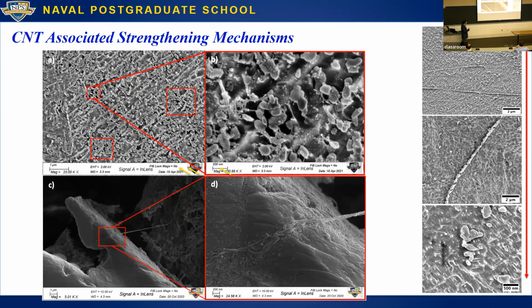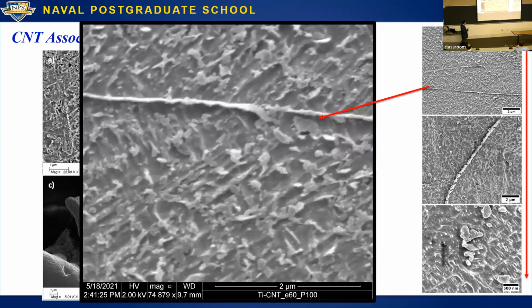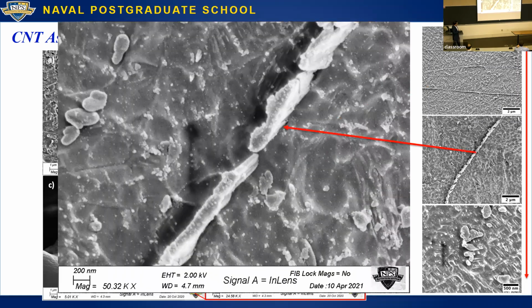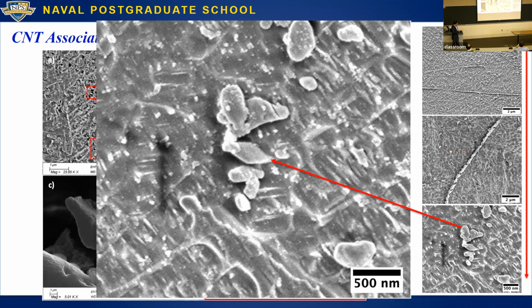And you also see them embedded here. These are long nanotubes that are going in and out of the surface of the structure. You only see this in the composite samples. And what happens to some of these nanotubes is they do react with the surrounding matrix, and they start forming these elongated carbides. We think this is essentially representing the transition between the nanotube and then reacting with its surrounding to form almost these lines of linear carbides, which is not a common morphology for titanium carbides. We're pretty confident that this is directly emanating from the presence of CNTs.